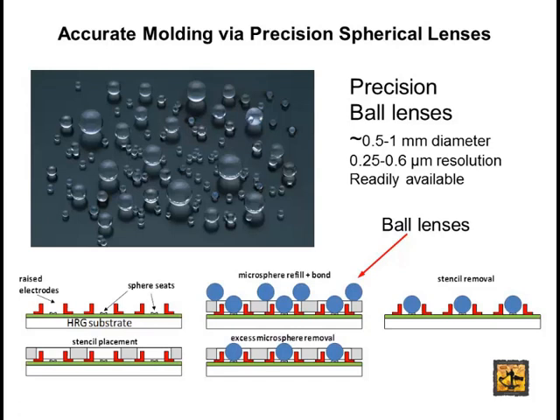And these types of lenses are used a lot in fiber optics for coupling light, and in lasers, for example. They use spherical lenses, and they have to be very accurate in order for the optical losses to be minimal. So you can get fairly inexpensive large-diameter ball lenses, about 1 millimeter or less, easily with about 0.6 microns resolution away from the perfect sphere.